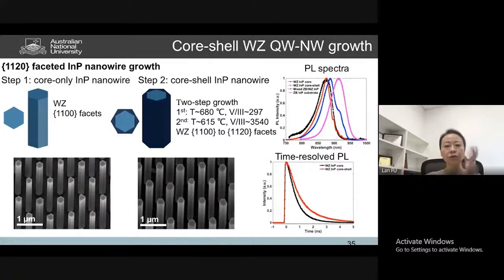So my student thought of another way: growing a Wurtzite-based core of only indium phosphide. Go back to the indium phosphide Wurtzite base. And then we promote a core-shell structure after that by introducing our low temperature, high V/III ratio recipe to rotate the facet and follow the bullseye structure of the indium phosphide base, because we're not introducing indium gallium arsenide there yet.